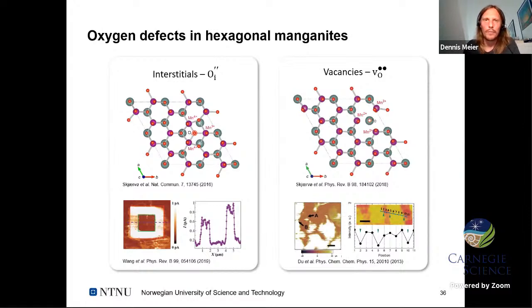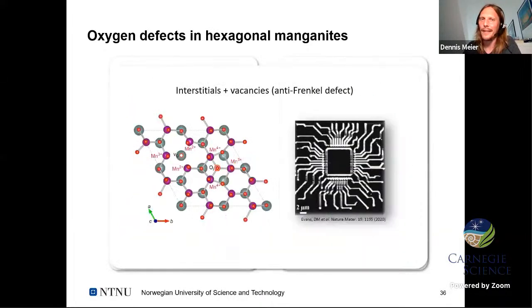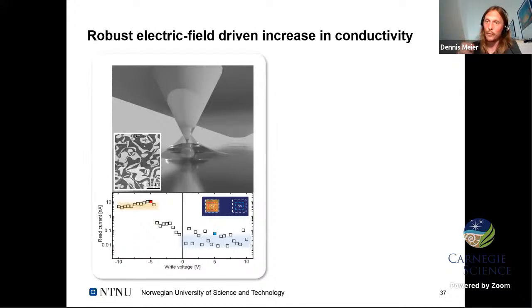This is now a little problematic because both defects are not charge neutral. They will induce gradients and so on. So we thought, why not try anti-Frenkel defects, so a combination of oxygen vacancies and interstitials, to control the conductance. I would now like to first show you how we created them.